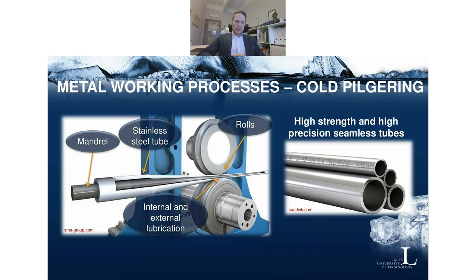Important to notice here is that we have an internal and external lubrication system for this process. So there is lubricant inside the tube between the mandrel and the tube, and there is lubricant on the outside between the rolls and the tube. The most critical one is obviously the internal one, which is